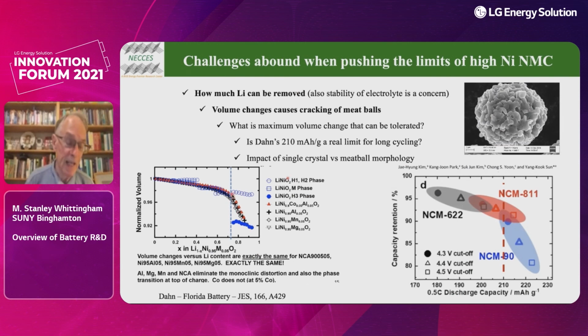I'll point out this is not a huge volume change. This is less than the volume change we see in TiS2 or in graphite itself. But this small volume change, when you pack these particles together, when they're crammed together, will cause the meatballs to crack. And Yang-Kook Sun has come up with the same idea. As soon as you get above about 60%, that's the same point here, then your capacity retention falls off the cliff. So the question we ask, and I'll let Jeff answer it in a moment, is 210 a real limit, or can we go larger?